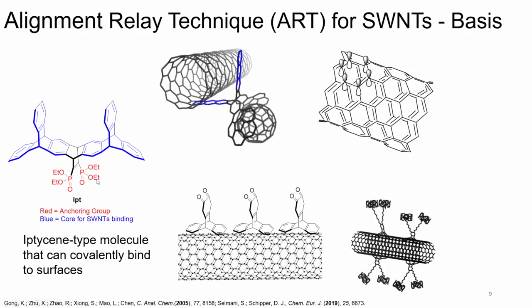So we have this added component here, I should add in the red. So the core for the carbon nanotube binding is in the blue, and in the red here is this anchoring group. So we can anchor this component here. This can covalently bond onto a wide range of surfaces that have been oxidized. So the ethyl groups displace the hydroxyl groups, and then we have a very, very strong bond onto different surfaces. So the molecule kind of won't budge. So it can't easily be removed, and it can't easily be washed away.